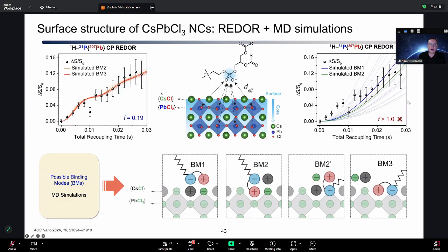Now, if we take our experimental results and we do some really nice MD simulations, these MD simulations were done with our collaborator Kovalenko with his group. We basically get 4 options here in terms of lowest energy performance. Okay, so you can have a system here where nothing gets cut off the surface, and you have the electrostatic charges here. In this case here, you have the electrostatic charges build where this cation interacts with this anion and it sits in the pocket, or vice versa.